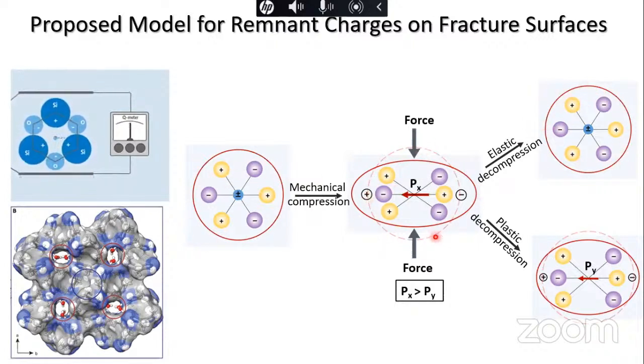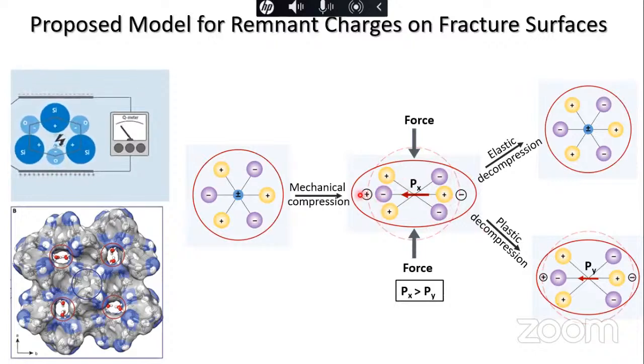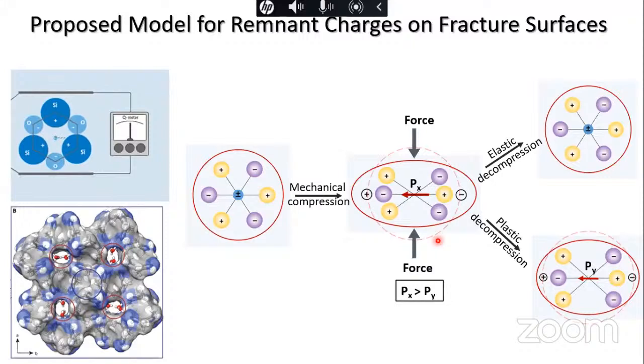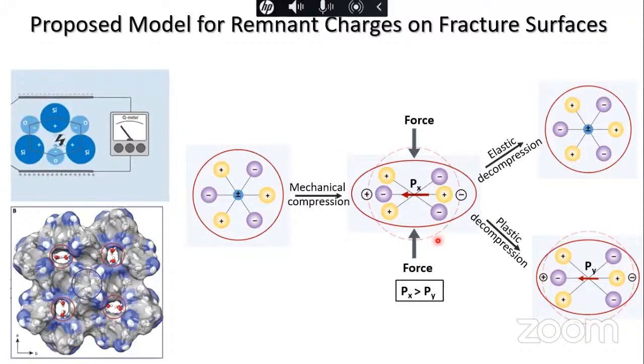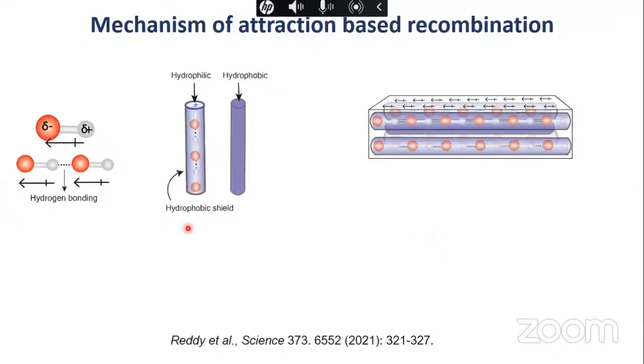For example, if it is not a purely elastic material and you leave it in between, you will still have some small partial charges. So we believe that in our case, once we break it, the crystal is not fully elastic. There is some kind of fatigue, because of which the charges are still present on the broken pieces, and that helps these crystals to come together and heal. That is what we proposed.